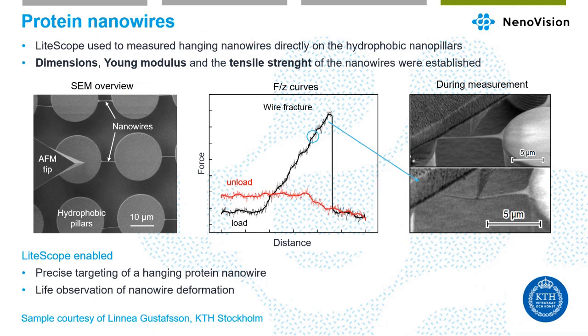Another example from protein nanowires is when the Lightscope was used to measure hanging nanowires directly on the hydrophobic nanopillars. So dimensions, Young modulus, and tensile strength of the nanowires were established and studied. If we have a look, there is an AFM tip, and here is nanowire deformation. We were studying both the elastic deformation and the plastic deformation. And at the same time, we were able to observe the nanowire live.